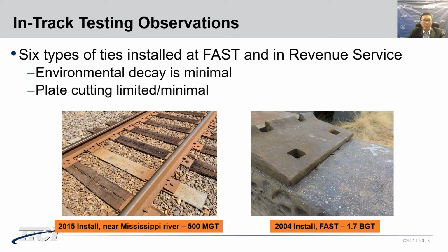In addition, a reduction in plate cutting on composite ties was observed when compared to wood ties. As shown in the photo on the right, the composite tie test zones with AREMA 14-inch plates installed at FAST in 2004 had less than 1/8 inch high rail plate cutting after 1.7 billion gross tons. For comparison, 3/8 inch plate cutting was observed in a controlled hardwood tie test zone after only 1 billion gross